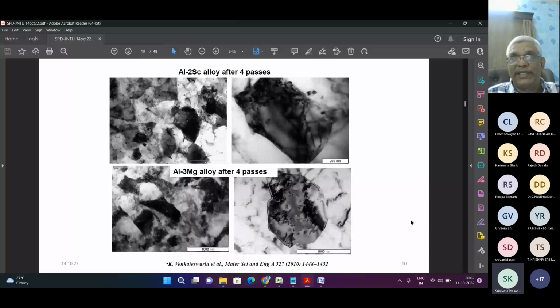Can we go on reducing the grain size like that? Professor Atul Chokshi from IISc Bangalore, Metallurgy Department, has taken nickel, aluminum and copper materials, and has done extensive studies, going on reducing the grain size by the powder metallurgy route and by severe plastic deformation processing. What he found is that below a grain size of 20 nanometers, there is not much difference. In fact, grain boundary sliding takes place, so there won't be any improvement in the yield strength. Only the ductility can be improved.